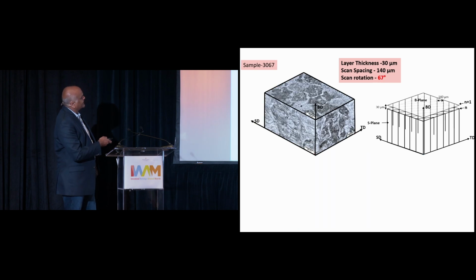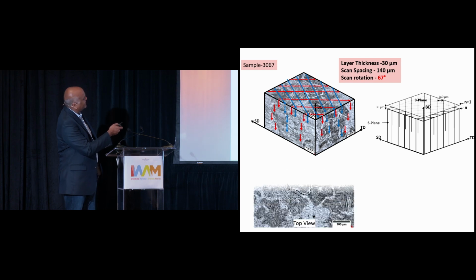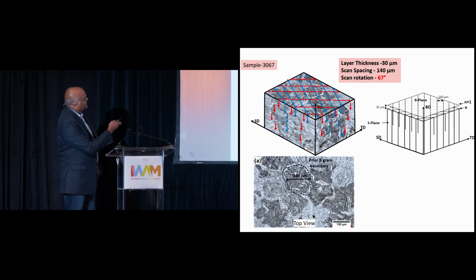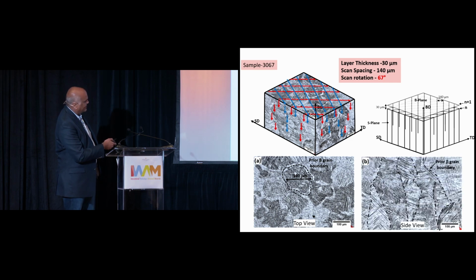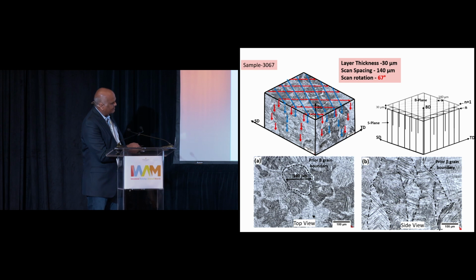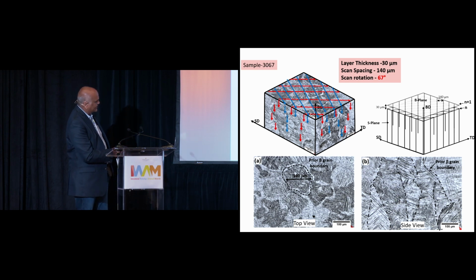Now if you keep the layer thickness at 30 microns but change the rotation to 67 degrees between successive layers, on the top you break the square grains, and on the side the columnar grains are also broken, but the grains are still oriented in one way.